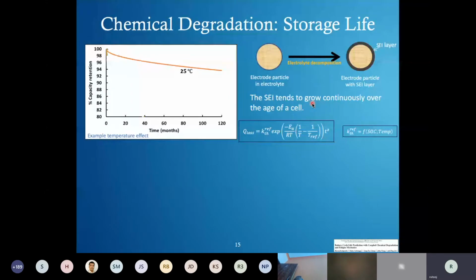Now the rate of these reactions is temperature dependent, like any other reaction. The higher the temperature, the higher the rate of reaction, and typically they follow something called Arrhenius behavior. What it means is you will have much higher degradation at 45 degrees Celsius than at 25 degrees Celsius, and much higher at 60 degrees Celsius than at 25 degrees Celsius. Whereas you will have lower degradation at 0 degrees Celsius when you just store the cell. Again, these are all example numbers. They may not apply to your particular cell.